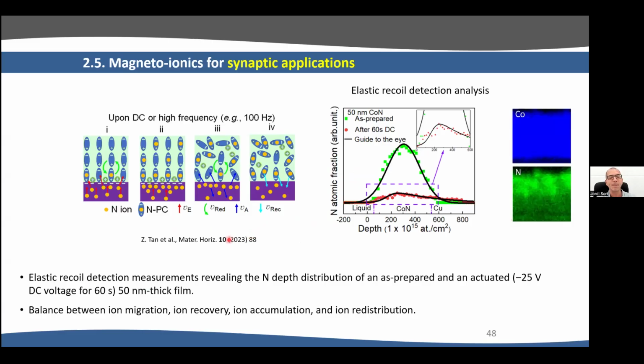So basically, what happens in cobalt nitride at the beginning is that the nitrogen is released from the film to the liquid in a layer-by-layer fashion, so you will expect nitrogen to be accumulated at the bottom of the films. But if magnetoionics is very fast, for thin layers in particular, at some point the nitrogen goes up, but all the propylene carbonate chains indicated here in blue get solvated with nitrogen ion. So basically we exceed the solubility limit of nitrogen in propylene carbonate.